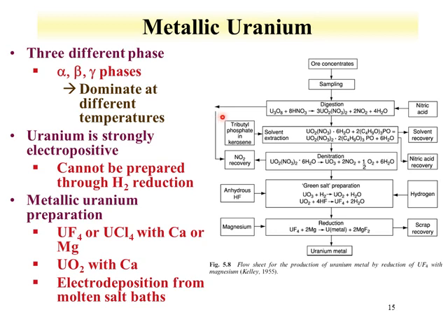So that means to prepare uranium metal, I have to use a different route, and what's done is shown here, where we make fluorides of uranium. We take those fluorides, treat them with magnesium metal, so a divalent metal or even a monovalent metal would be sufficient to reduce uranium from the +4 to the metal state.